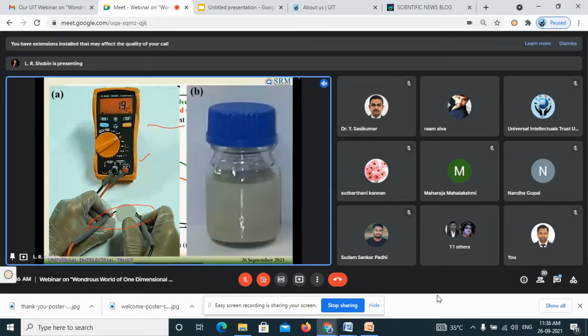And if you check the film's resistance, it falls to 1.9 ohm, almost 2 ohm, which shows that these films are metallic in nature. The amount of PVP is reduced in the film, which shows that if the PVP content is more in this film, you will have an insulating film. You won't get a conducting film out of it. These films are conducting in nature, so there is a small amount of PVP, or I would say I have lost the excess PVP from the